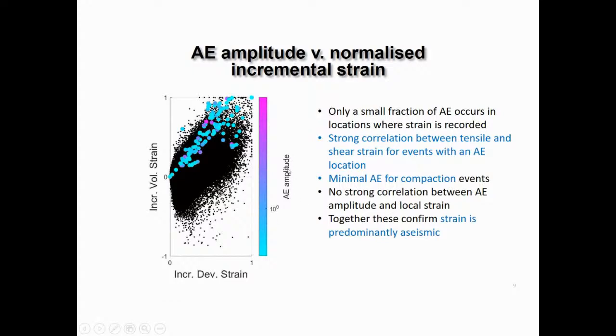And this is the acoustic emission amplitude plotted here. And what we find is that only a small fraction of acoustic emissions occurs in locations where the strain is recorded. We've got strong correlation between tensile and shear strain for events with an acoustic emission location. And we've got minimal acoustic emission for compaction events. No strong correlation between acoustic emission amplitude and local strain. So these confirm our inference from summing up the seismic moments that the strain is predominantly aseismic.